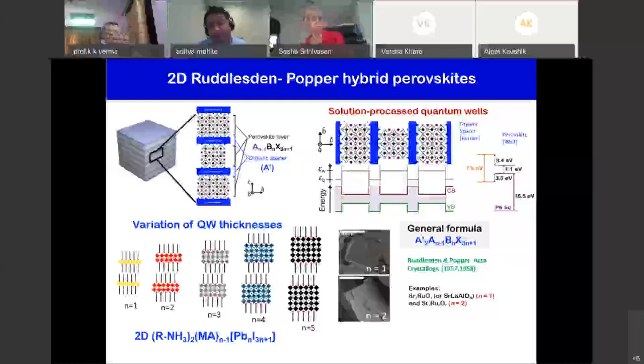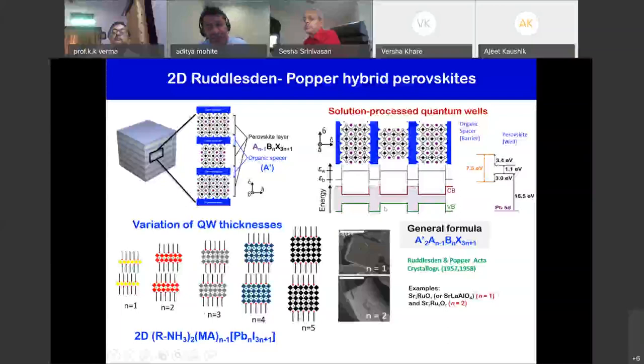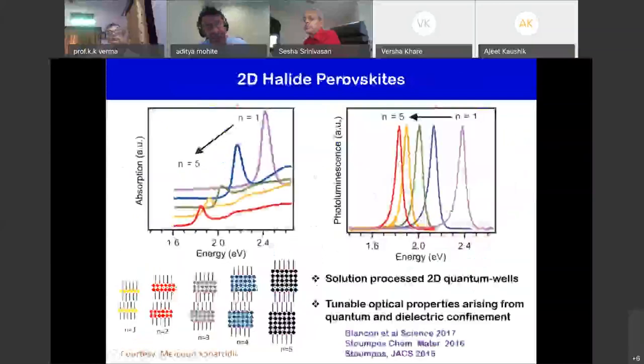Thank you. Okay. And so these two-dimensional perovskites, you'll see these structures that we made. And as I mentioned, these are solution processed materials as well. And so you have these structures which you can tune very nicely. And they've been known because they were very, very stable. And so you can actually look at the absorption spectrum. This is a function of N value, the perovskite layer thickness. And you can see that you can tune the energy very well. You can tune the photoluminescence and emission quite well.